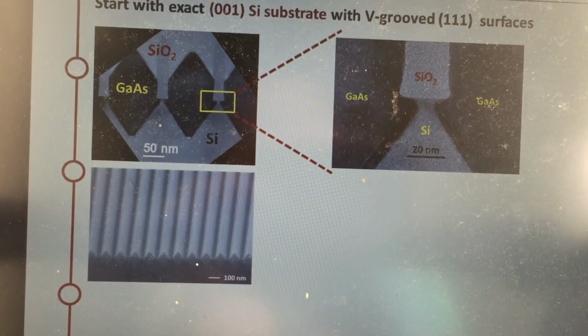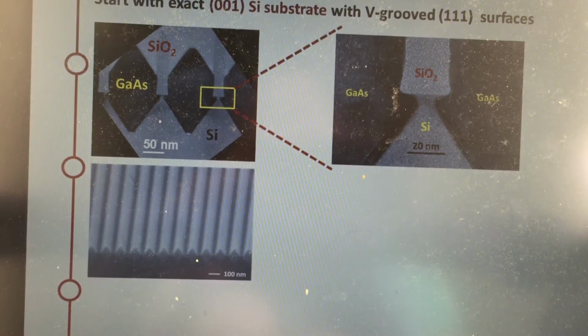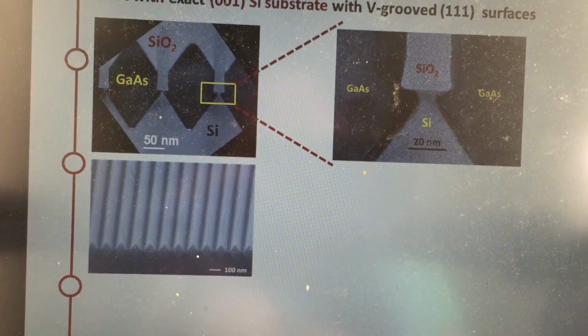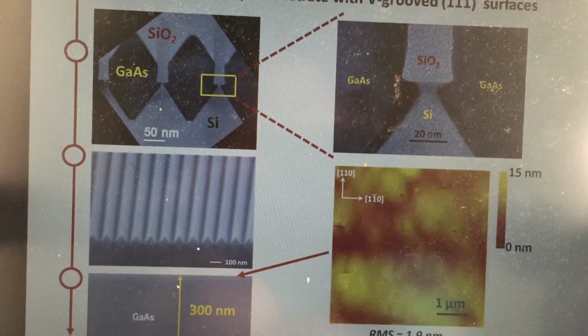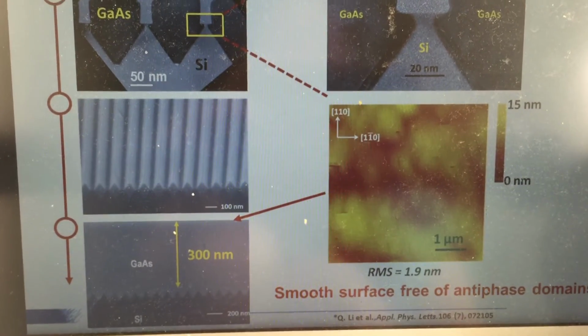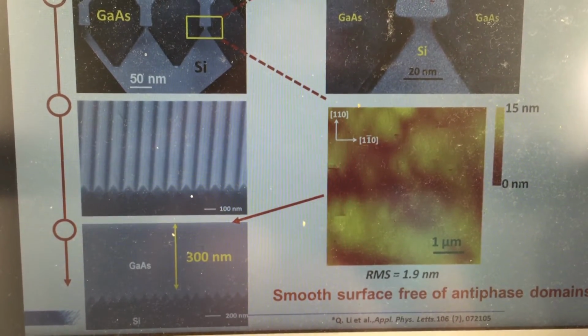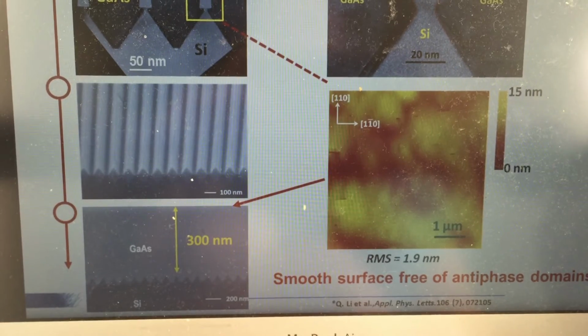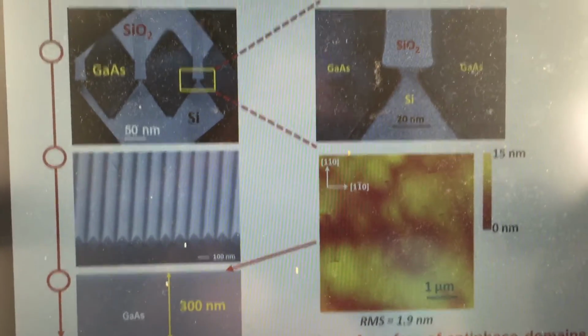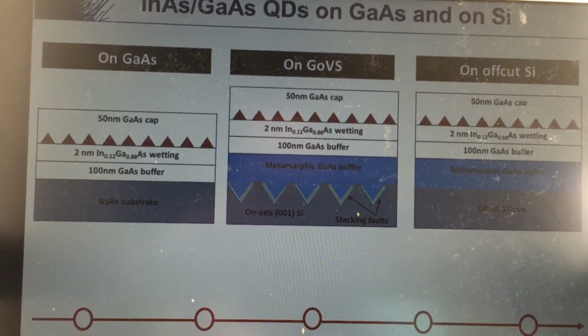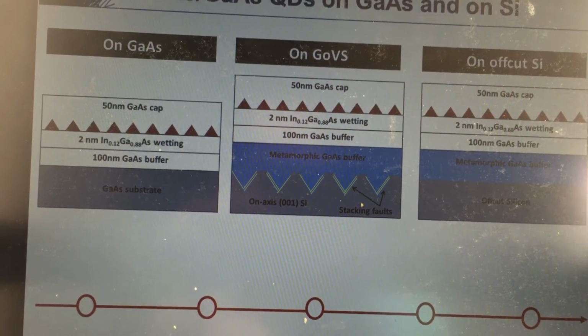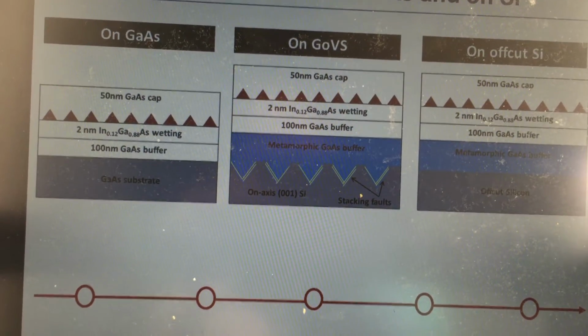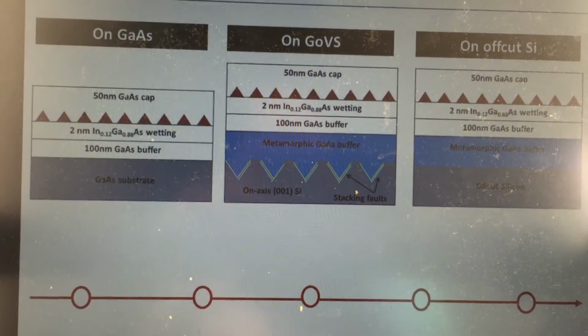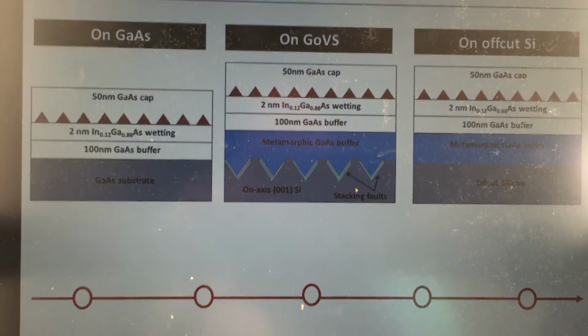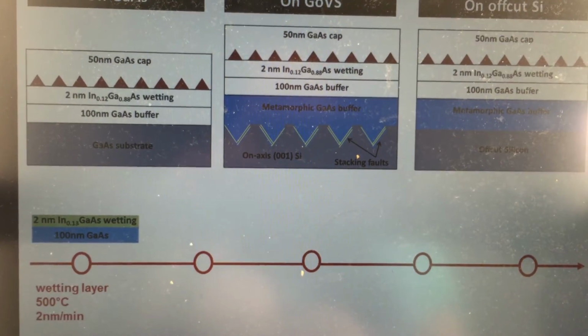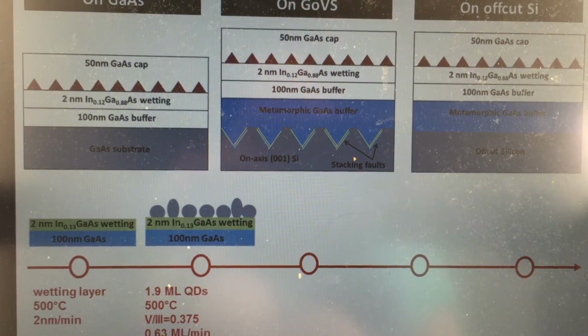After removing the silicon oxides, we then use the GaAs nanowires as seed layers for the subsequent lateral overgrowth, and we were able to achieve thin GaAs films with a smooth surface free of antiphase domains. We then grow the quantum dot structures on the GoVS substrate, together with the lattice matching GaAs substrate and our off-cut silicon template. After the buffer layer formation, the quantum dots were deposited.